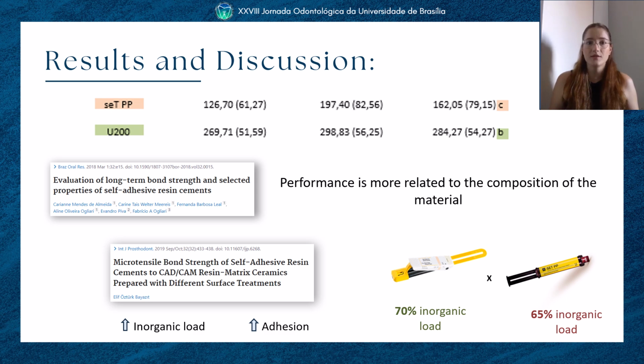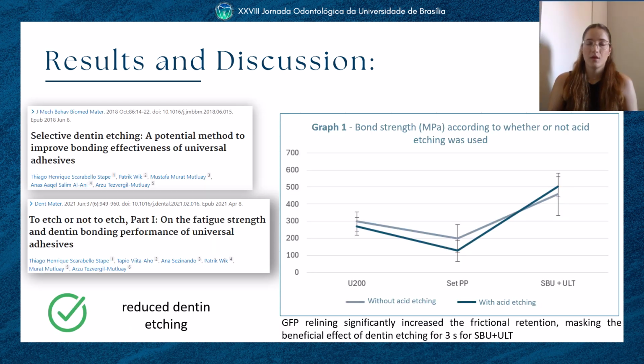For the SeT PP and U200, their performance is more related to the composition of the material, and the higher the inorganic load, the higher the adhesion, and this can explain why U200 had a better performance. Although some studies show a better performance of reduced dentin etching, in this work there were no statistically significant differences, which could be explained by the GFP relining increasing the frictional retention, masking the beneficial effect. However, we can observe a tendency to improved bond strength in the SBU plus ULT group, as we can see in graph 1.